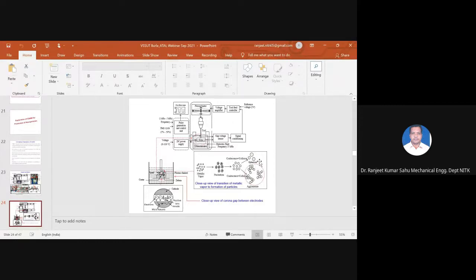You are getting spherical particles of defined size. When the coalescence rate is greater than the collision rate, then you will get agglomerated particles. That means bigger size particles we are obtaining. So this mechanism we have to tune by the various process parameters and also the surrounding environment. This is the main physics behind it in our case.